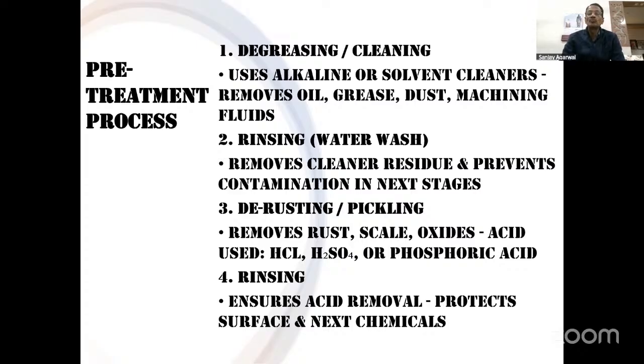First is degreasing. Here we use a chemical, an alkaline solvent, which removes grease, dust, or any machining fluid on the parts. Second is rinsing, where we wash the component in DM water to prepare it for the next stage, so there is no contamination. Third is derusting or pickling. We remove rust, or any carbon layer on the component. Here we are using acid: HCl, H2SO4, or phosphoric acid. Fourth is the rinsing operation.